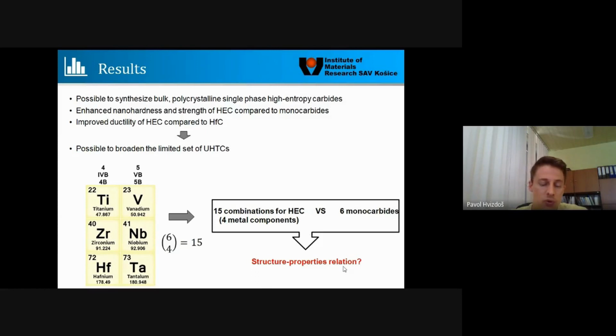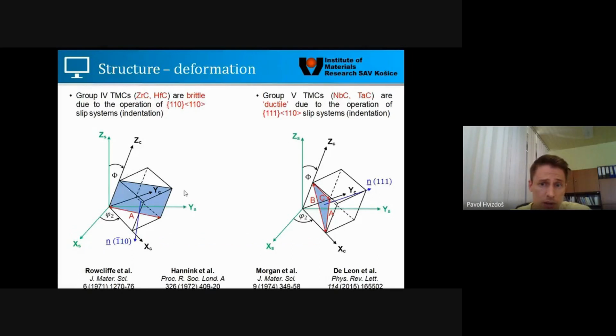So the question of course still remains: what is the structure-property relation, at least regarding the specific material that we tested? First we have to start at some basic levels. Group 4 transition metals, meaning zirconium and hafnium carbide in our case, are basically brittle. Indentation techniques and also TEM work revealed that they have a dominant slip system of the so-called diagonal plane, the 110 plane, with a slip direction of 110.